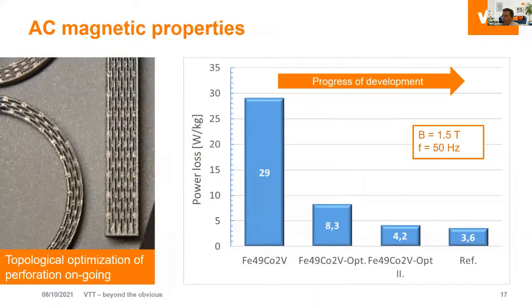And if we look at how it affects the material behavior under an AC magnetic field, in the case of the bulk component, the power losses at 50 Hertz are something like 29 watts per kilogram, while the laminated reference material has power losses of 3.6 watts per kilogram.